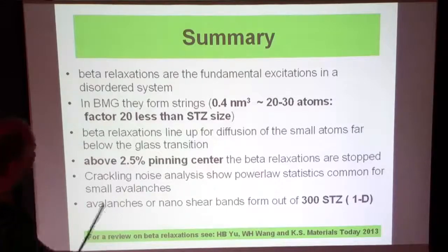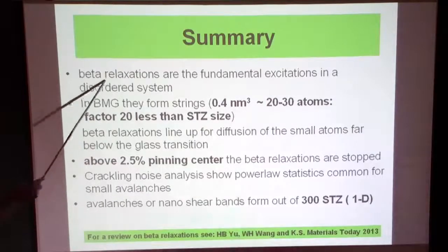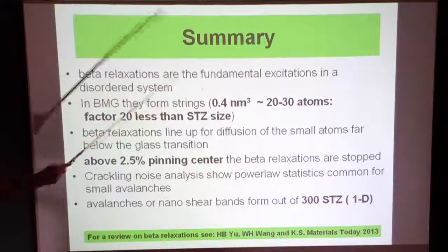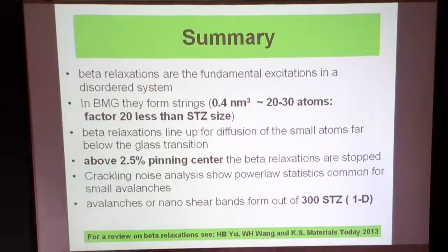Let me try to summarize that also. So we think that we see the beta relaxations as the most fundamental excitation in disordered systems, not speaking about the cage breaking stuff. The cage breaking stuff is in picoseconds. At least from the simulations, we know that they have a cage and the atoms move only a little bit to make from a 9-fold next neighbor shell to a 10-fold one, or so. Like Takeshi is discussing that, and this is most of the time reversible. So these are the ones which then change the configuration, or on its way actually, or make diffusion possible, or make aging, or make then the rejuvenation also.